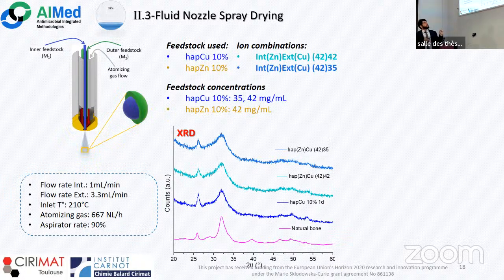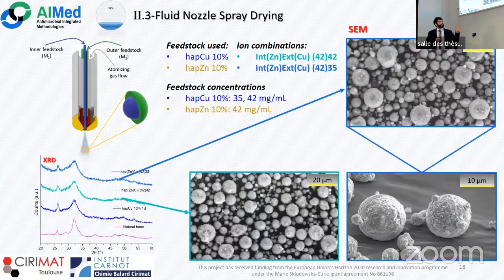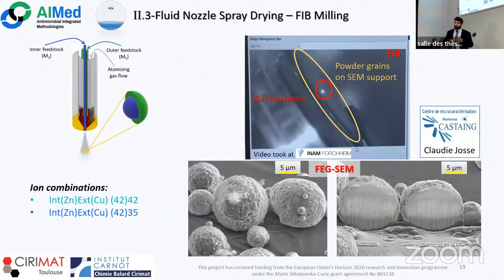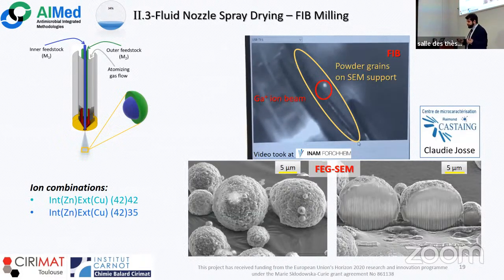We can observe at first that the XRD patterns are coherent with the dried powder and, of course, with the natural bone. And differently from the usual apatite crystals, we can observe that the morphology is quite controlled. And even looking closer at the spheroids, we can observe this surface rugosity that could suggest that we really had an agglomeration of the apatite nanocrystals that we have in solution. At this point, it started one of the most challenging parts of this thesis work, to properly characterize them.